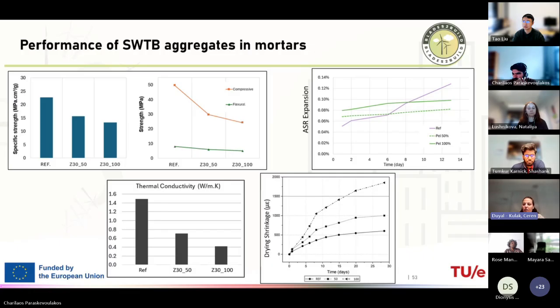Since the density of the mortar is decreasing a lot, we have also discussed the specific strength, which shows a decrease as expected, but still we have an acceptable level of strength. Also, we tested durability on ASR expansions because the waste has a lot of glass in it, and we also checked the drying shrinkage because the aggregates have a lot of porosity in them.